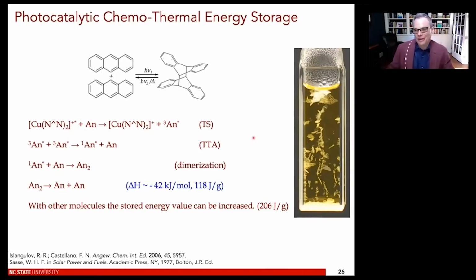The interesting thing about this particular dimer is that when it's melted, it has a negative enthalpy. So it's storing energy in a metastable state as a solid. And of course, you can put this in chemistry terms, so it's minus 42 kilojoules per mole, but in more engineering terms, it's storing 118 joules per gram of material. And then other anthracene derivatives can increase the energy value up to even 200 joules per gram. So we tend to think that this is an interesting idea because you can do